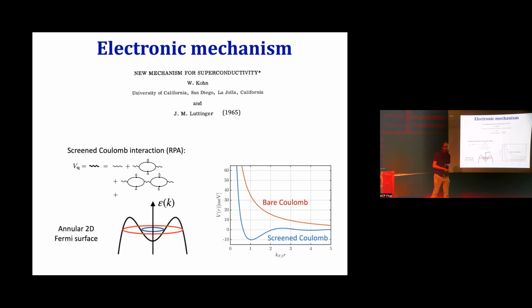This is the right shape of the Fermi surface for the normal state of trilayer graphene. And the striking thing is that you see that the effective screened interaction has these wiggles. If you Fourier transform this effective interaction, you see all sorts of characteristic wave vectors of the underlying Fermi surface. Basically, if you put a charge in this liquid of electrons, it responds, it tries to screen, and it overscreens. This is basically this phenomenon. You see that this interaction actually goes negative. It means attractive. And if the region where it's attractive is just right, you can actually get this effective interaction